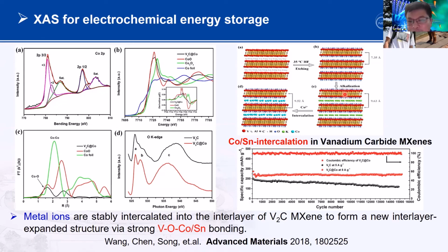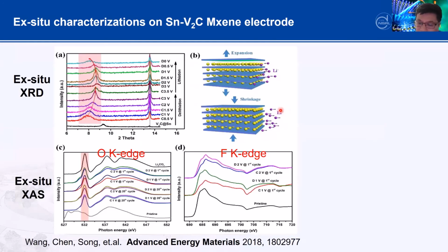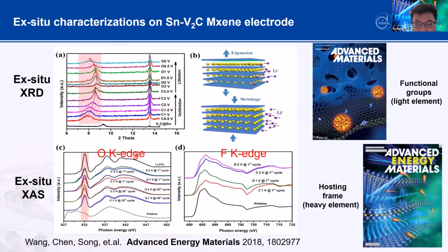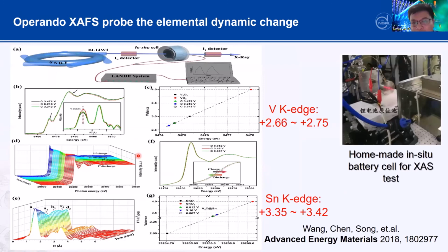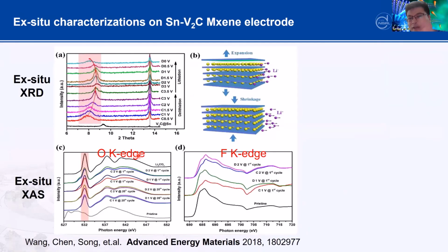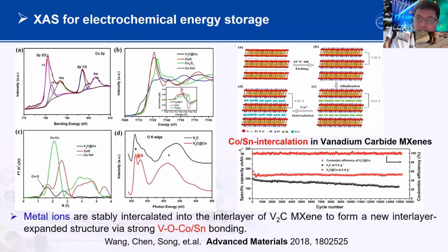You are really right about the lithium storage. This is not a real lithium ion battery. This is a battery combined with a capacitor, that means a battery with capacitor behavior. As you can see, with this layered structure, the stability first comes from the stabilization by the intercalating metal, because they form this kind of chemical bonding. Meanwhile, we also understand the functional group contributes to the lithium storage, and that not only the vanadium but also the intercalated outer metal contributes to the lithium storage performance. So this is a battery combining the capacitor, and the intercalating element really works for this stabilization. As you can see, this can really go to very long cycle numbers.